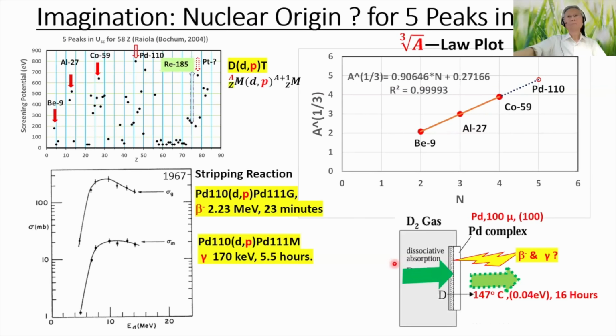We may use Iwamura's early device to verify this nuclear origin also. When the deuterium gas is passing through a palladium thin film with 100 surface, if the flux peak appears near 147 degrees C, keep this temperature for 16 hours, then measure the beta and gamma radiation immediately after the experiment. It may verify its nuclear origin as well.